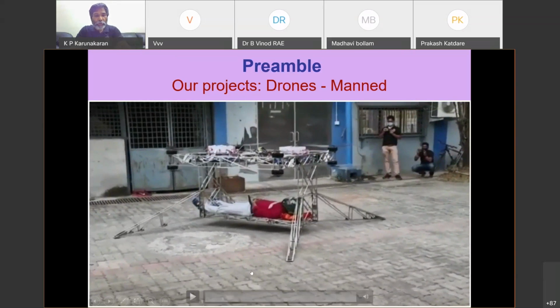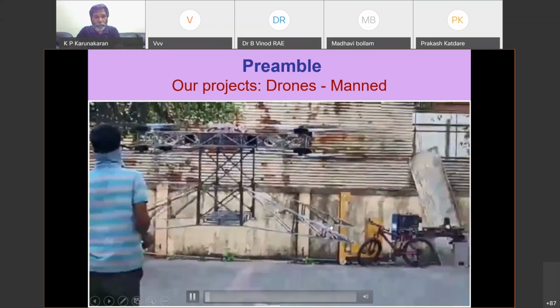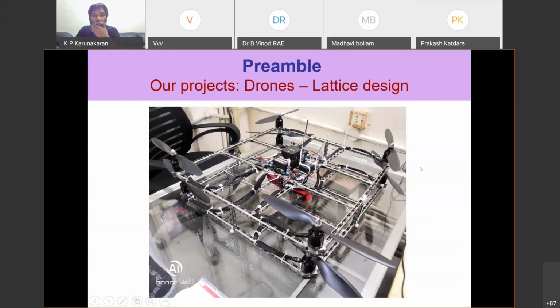So since then, we reduced the weight of it. So we will be flying. We have reduced by about 40 kilo weight. So I'm sure it will be able to fly very well. Okay, so that is one. And then in that case, they are all fabricated out of 10 by 10 square tube, 1 millimeter wall thickness, stainless steel 304. Now, using the same tube, we fabricated, I think you are able to see, we fabricated this.